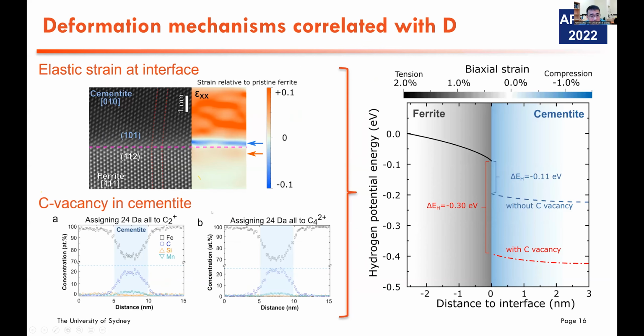So with these two pieces of information, the first one is that we observe elastic strain towards the phase boundary. And the second variable is that we can get the existence of carbon vacancy in our cementite, because even if we overestimate, the carbon value is still less than expected. So we reasonably expect that carbon vacancy will be in there in the cementite, and some other literature shows similar conclusions.